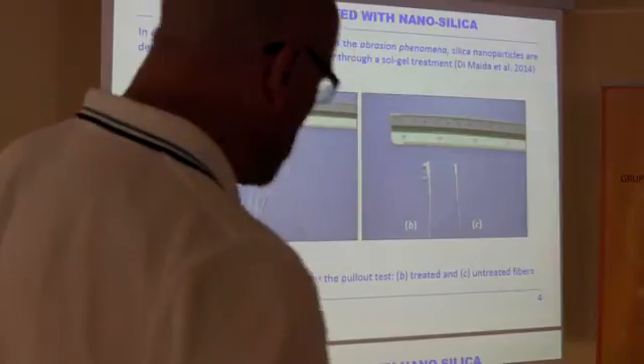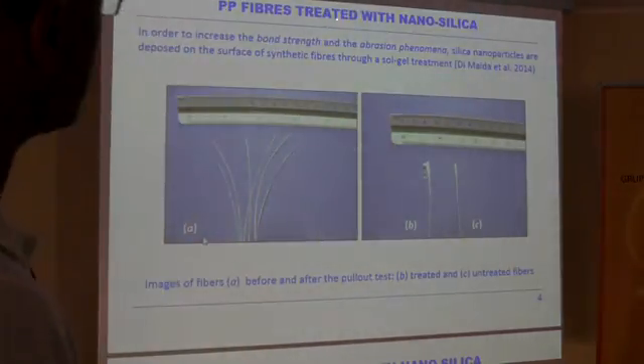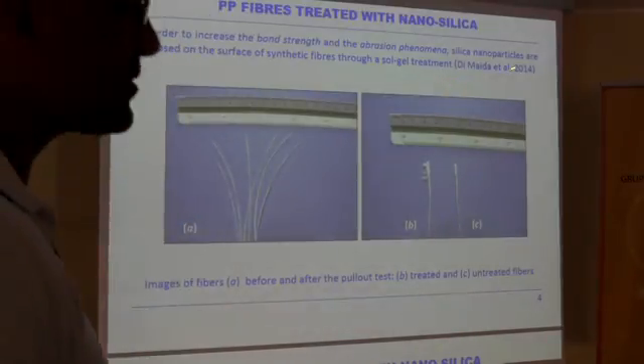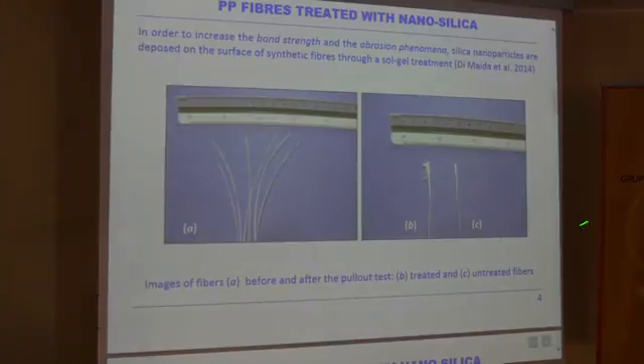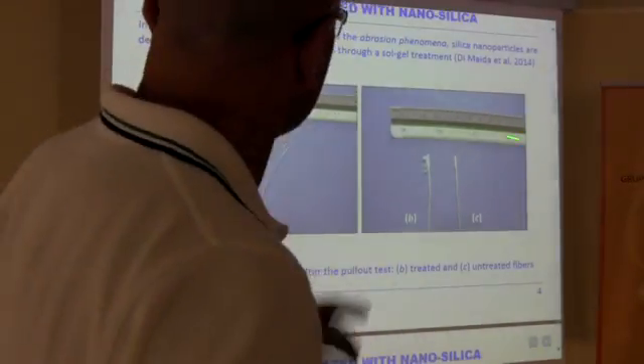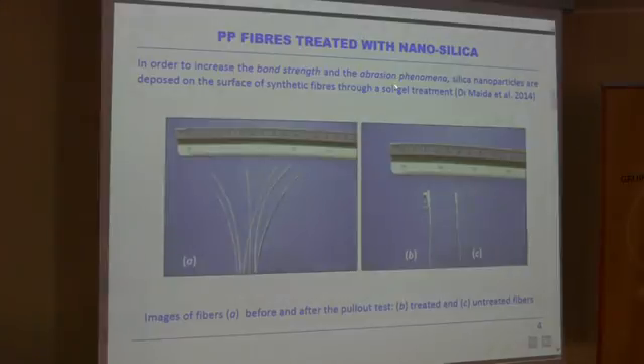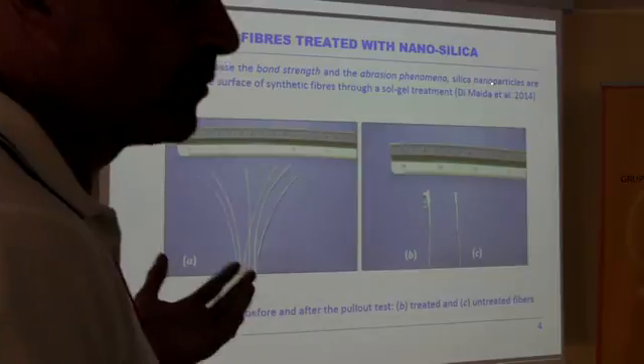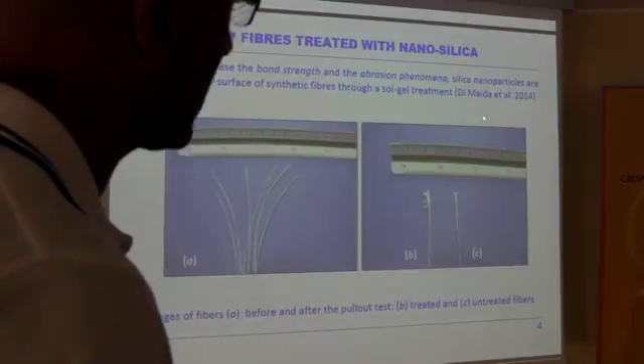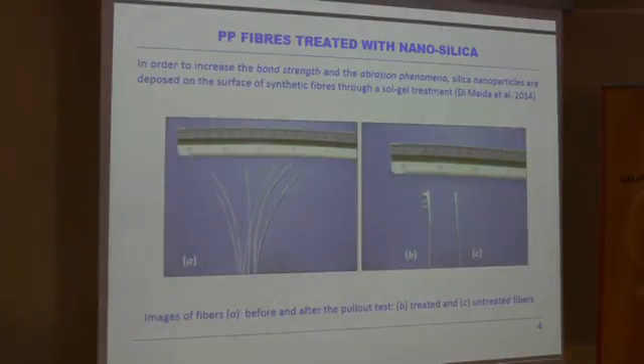However, in order to remedy the weakness of polymeric fiber and to increase the bond strength and the abrasion phenomena, we propose a treatment of the fiber surface with silica nanoparticles, which are deposited directly on the surface of the fiber by using a sol gel treatment. This treatment has been illustrated in a previous work by Dimaida and other co-workers.